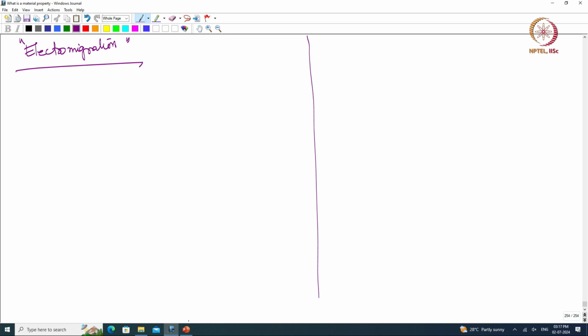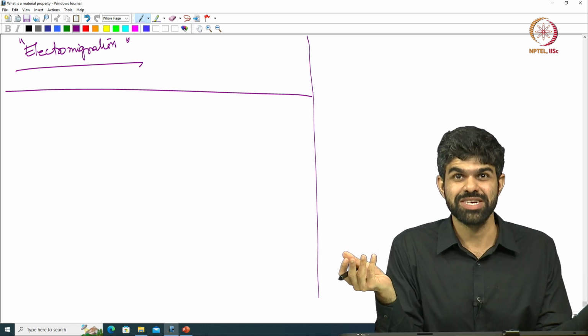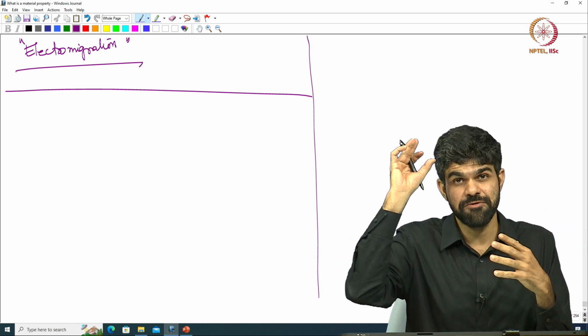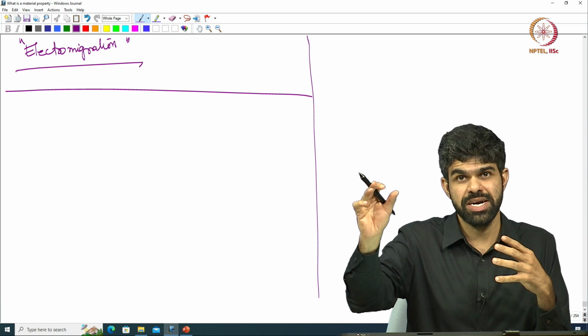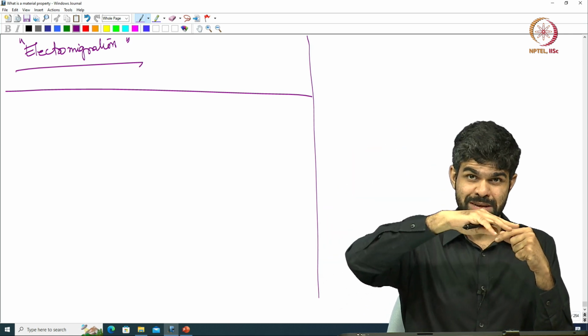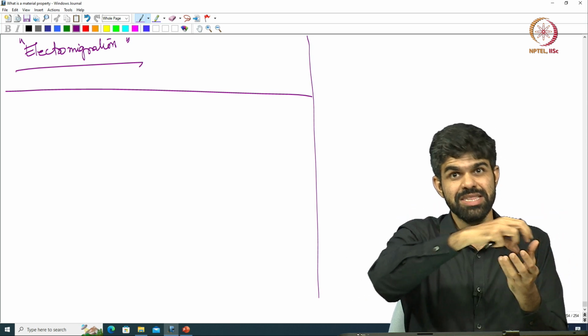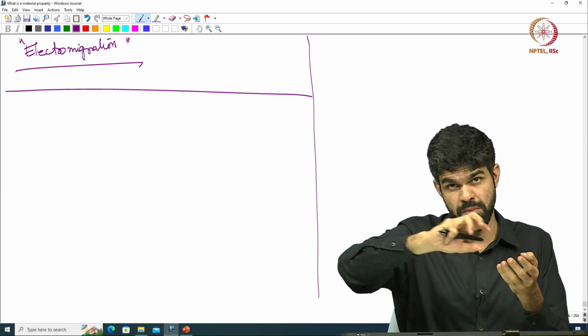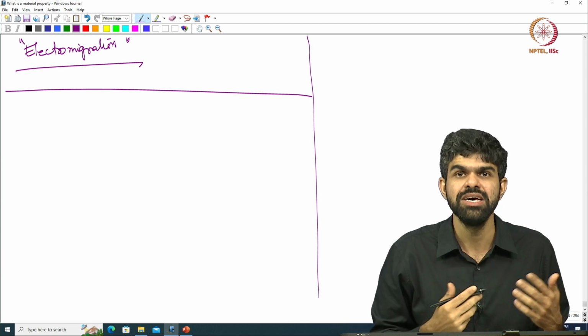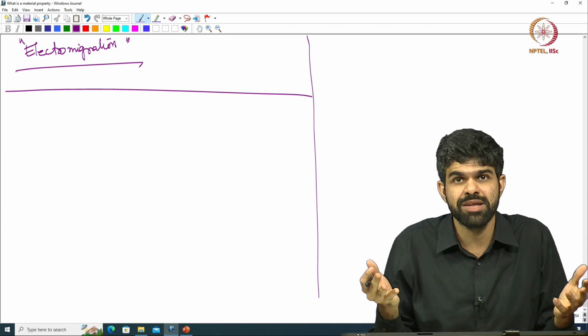So Onsager's theory explains electromigration. Simple Ohm's law does not explain electromigration, nothing else explains electromigration, but this Onsager's theory couples the force on electrons, which lets them move, and doubles up as also a force on atoms, and then it makes them also move from their equilibrium positions. So there is going to be electromigration, which is a problem that you want to avoid in most cases.